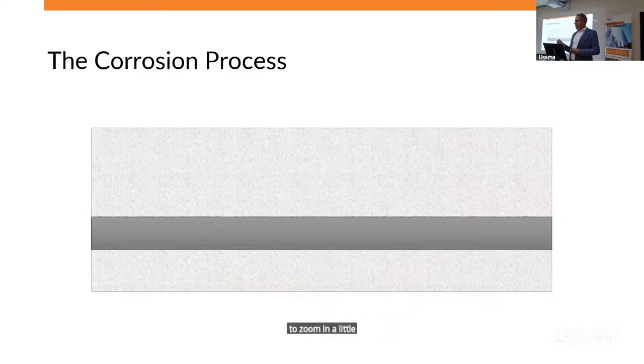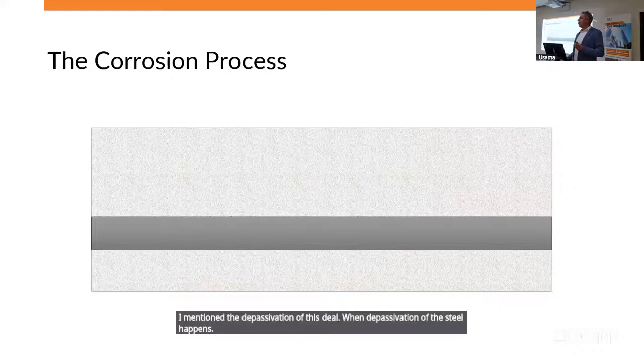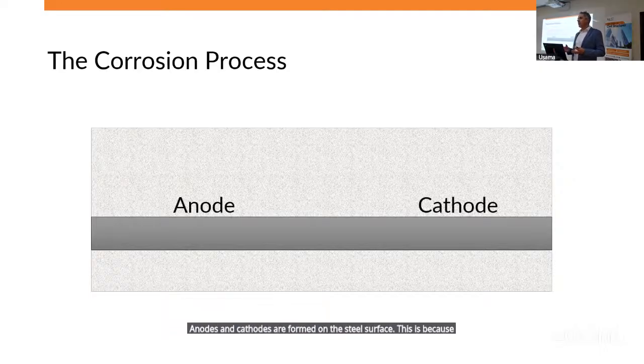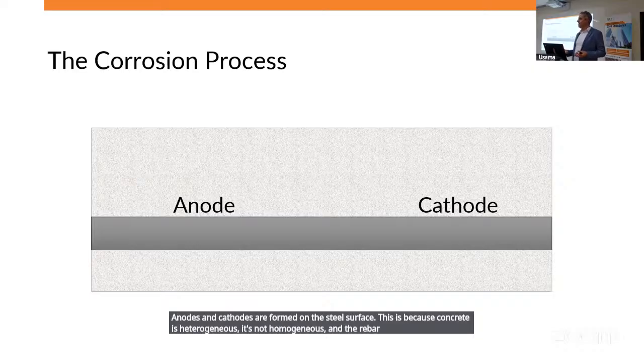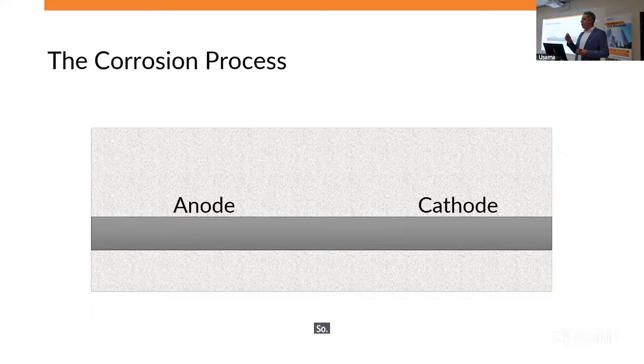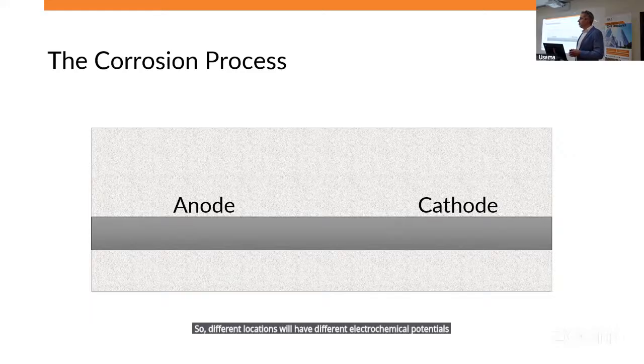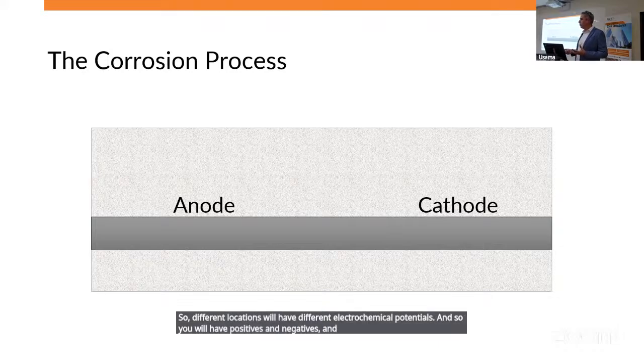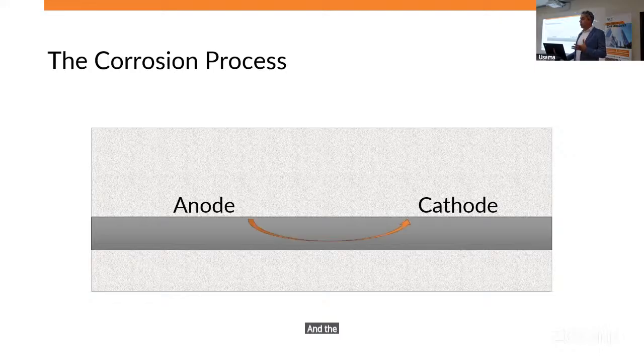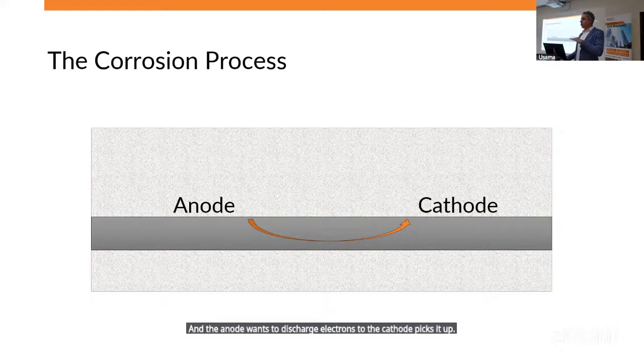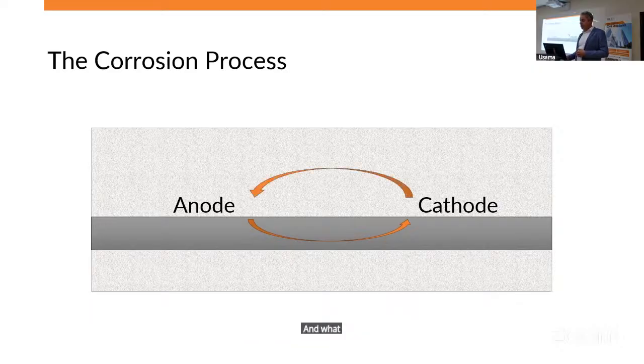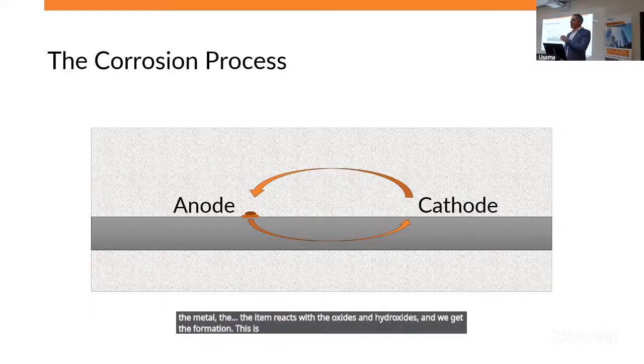To zoom in a little bit more in understanding the corrosion process, I mentioned the depassivation of the steel. When depassivation of the steel happens, anodes and cathodes are formed on the steel surface. This is because concrete is heterogeneous, it's not homogeneous, and the rebar itself, steel, also is a heterogeneous material. So different locations will have different electrochemical potentials. And so you will have positives and negatives and electrons wanting to move. The anode wants to discharge electrons to the cathode. The cathode picks them up. A surface reaction happens at the cathode surface where hydroxides are formed. And what happens at the anode is loss of metal. The iron reacts with the oxides and hydroxides, and we get the formation of the rust product.